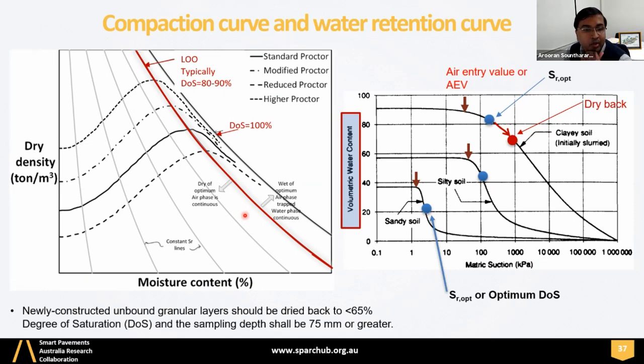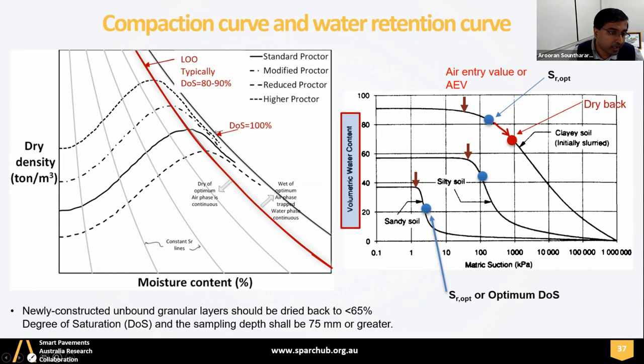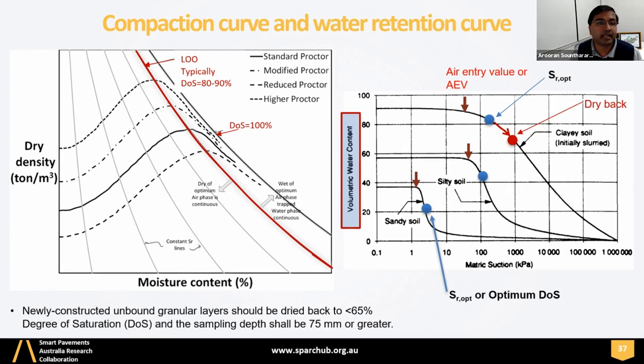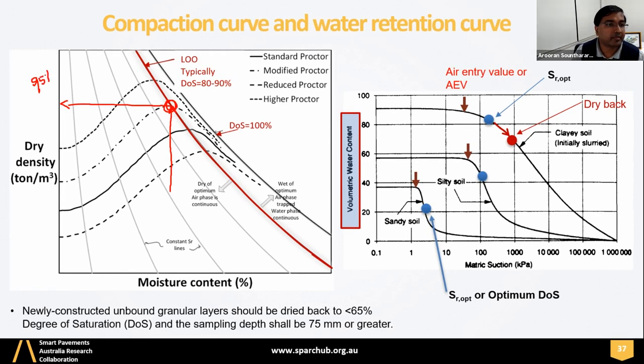Right. So compaction. After you analyze your performance in the laboratory, then you have the performance criteria, and now you are ready to compact or construct your pavement. So how do we compact pavement? Normally, there are two different compaction curves here. I would normally target modified compaction here, because modified compaction energy is normally used in Australia. So what happens here is you target optimum moisture content and then maximum dry density in the field. And normally we allow 95 to 98 percent relative density to be achieved in the field, right?